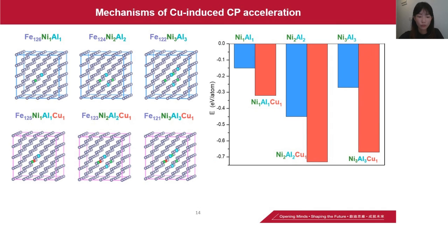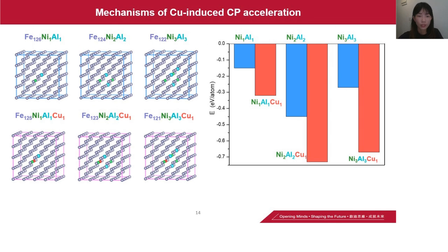So, from the above results, we demonstrate that copper is effective in not only promoting the continuous nickel-aluminum precipitation, but also in suppressing the discontinuous precipitation at grain boundaries. Well, for the mechanisms of copper-induced continuous precipitation acceleration, we did some first principles calculation to see the effects of copper on the acceleration of the CP.